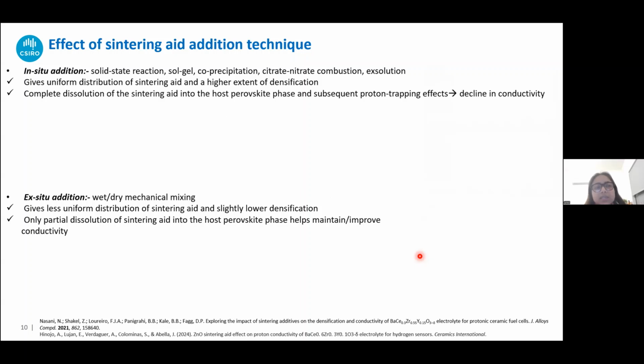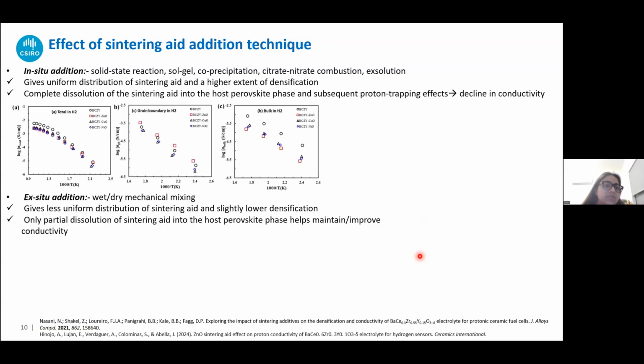However, in some cases, it also leads to complete dissolution of the sintering aid into the lattice structure of the BCZY. There are studies in the literature where they have used the sintering aid and that has removed quite a bit of the cerium or the zirconium from the BCZY lattice, and that has led to subsequent proton trapping effects that drop the conductivity.